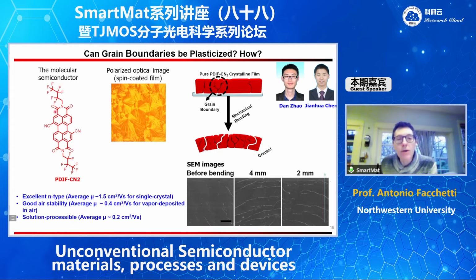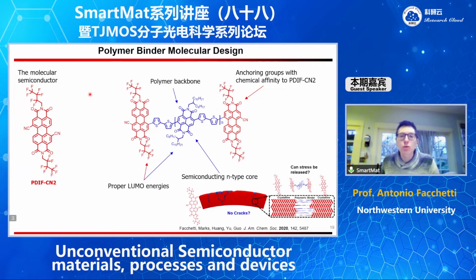So how can we try to plasticize this film? The way we did it is to design a polymer which has a polymeric backbone, but then it has an end unit which has a sort of molecular recognition with the small molecule. And our hope was that this additive will segregate at the grain boundaries of the film and somehow plasticize them.